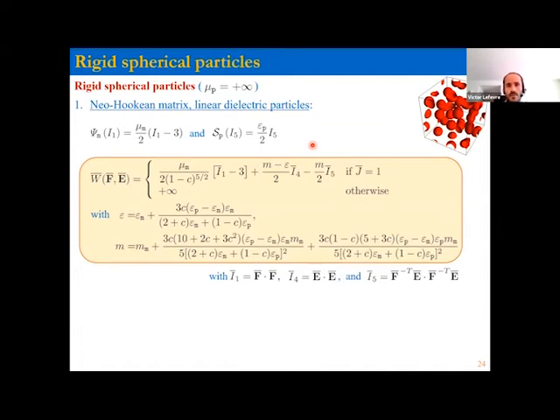And you can see in there that you have the shear modulus of the matrix that enters in the formula. You have the permittivity of the matrix. You have the electrostrictive coefficient of the matrix. You also have the volume fraction of particles as expected, c, that shows up here and there. And we also have the initial permittivity of the particles, epsilon P, that appears in the formula. So as expected, both the behavior of the two phases and the content appear in the formula, and this is specific to isotropic distribution of spherical particles.